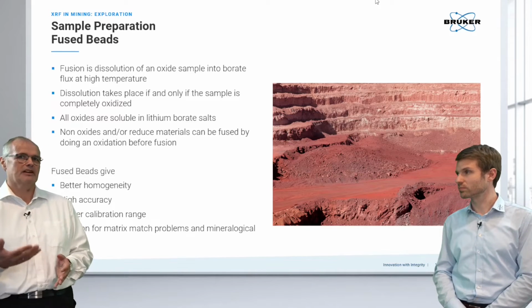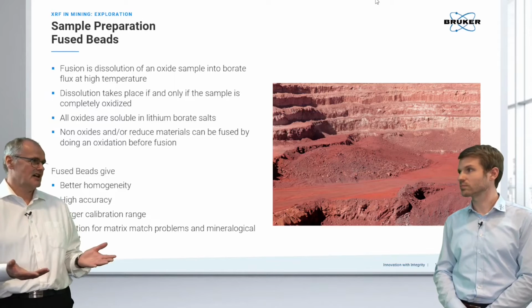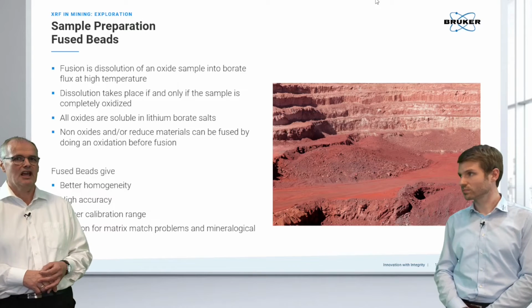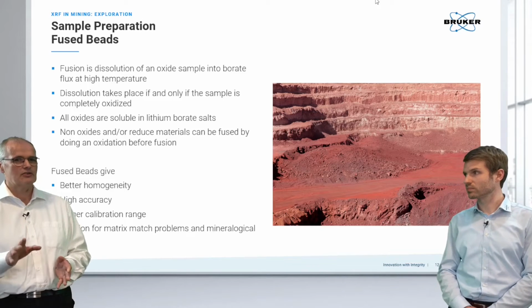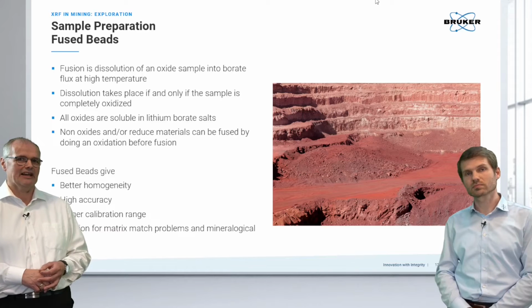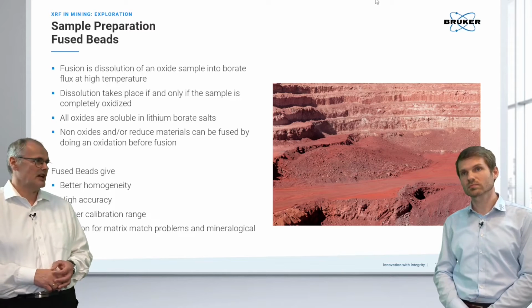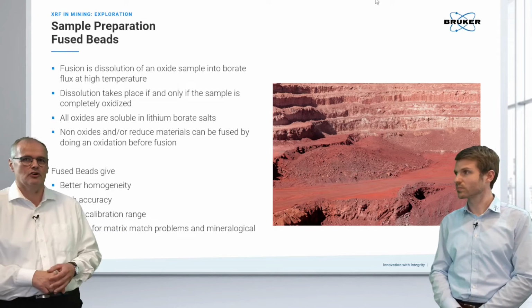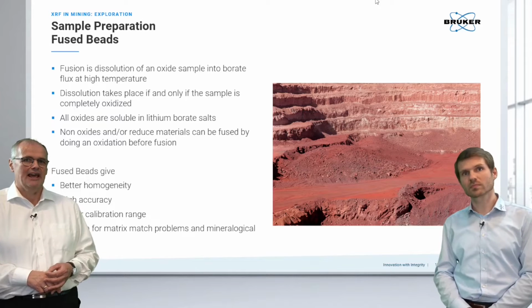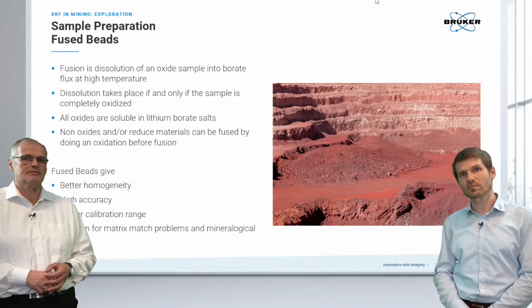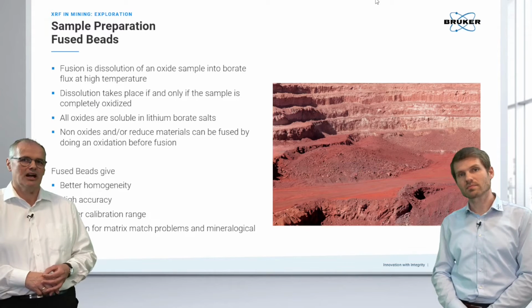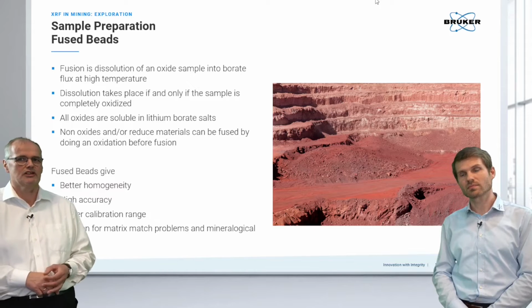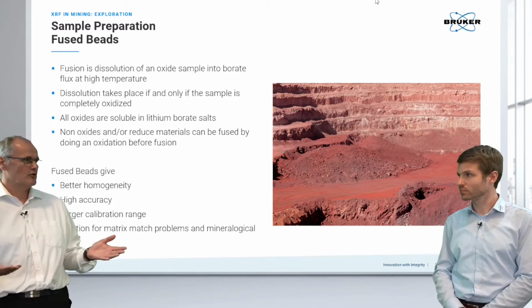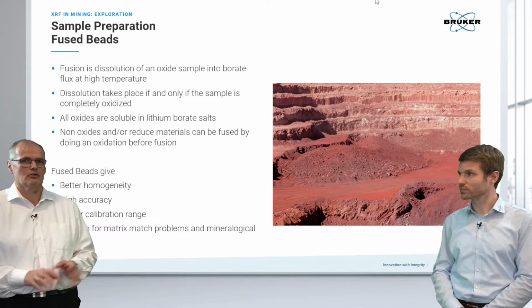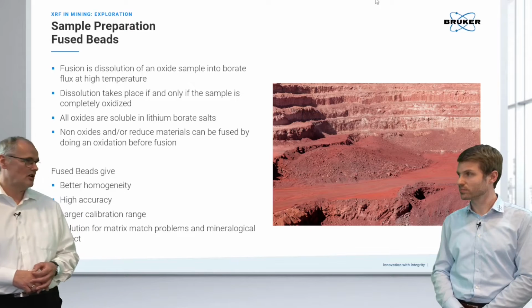And this gives better homogeneity, and this basically enhances accuracy. And also the dilution helps to analyze very accurately the major elements when we think about iron ore resources. And the dilution also helps with a match of the matrix and the mineralogical composition to the certified reference material. So those are the nice things of fused beads.